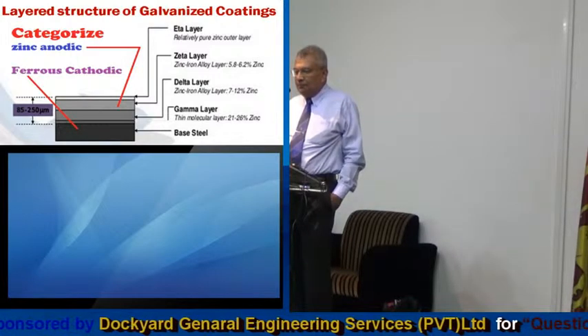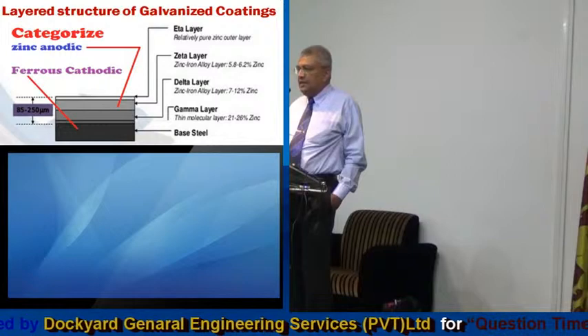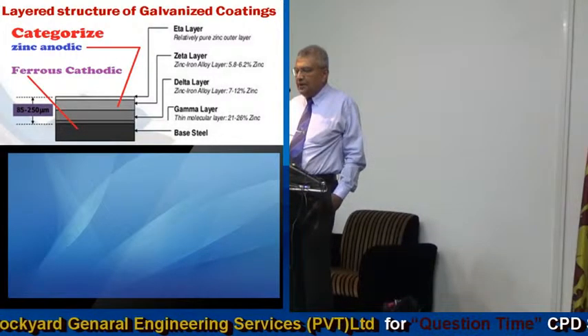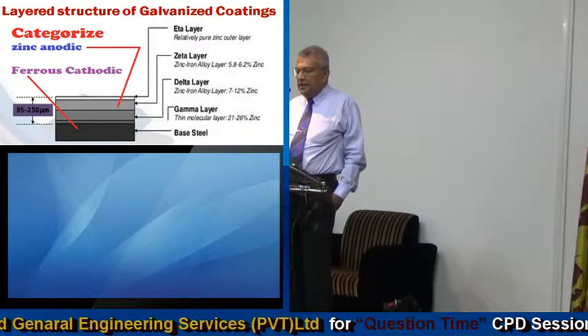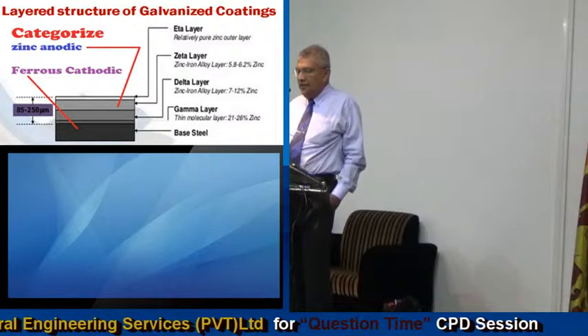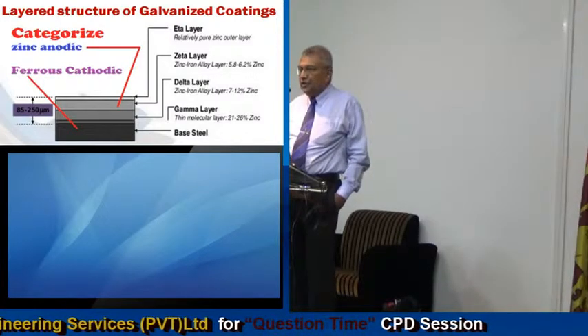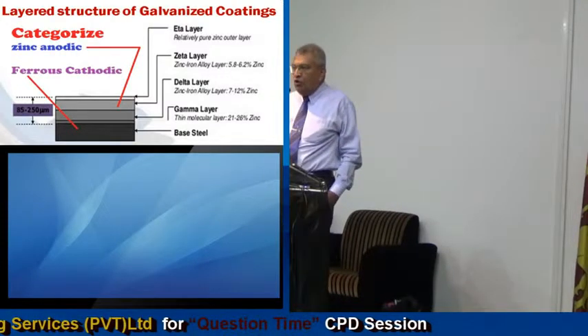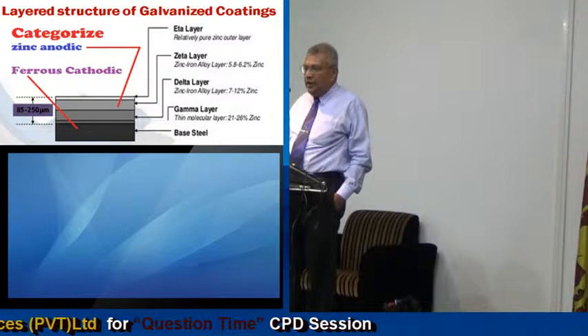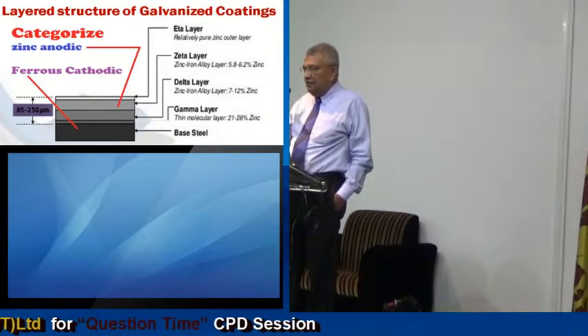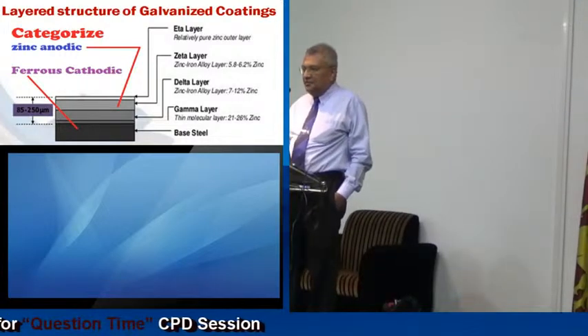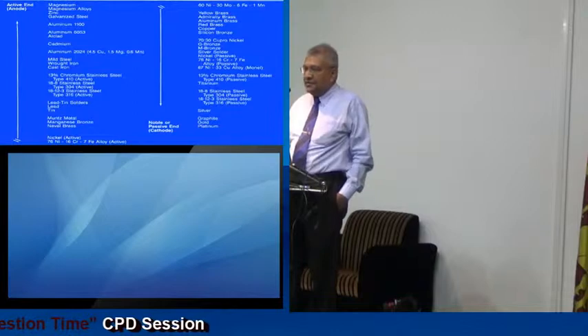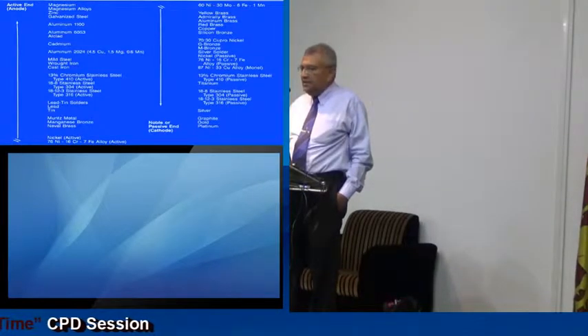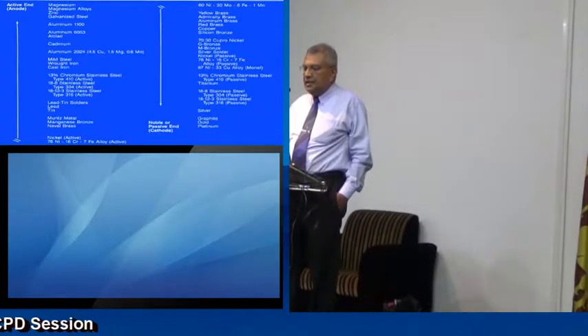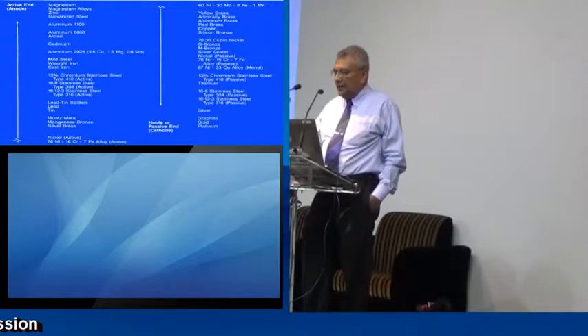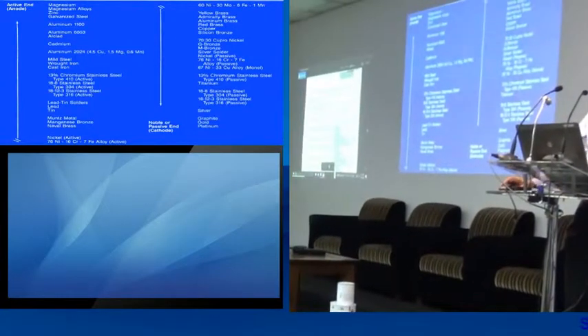We will show you why you have to paint it. This is a cross section of the galvanizing. As you see, the base steel, then the gamma layer, then the delta layer, zeta layer, and the eta layer, which is 100% zinc. Now that is the DFT, 85 microns or 250, whatever thickness you build. Now we know the ferrous is always cathodic and the zinc is always anodic. So we have a combined couple put together, because the anode always sacrifices in front of the cathode. So this is the sacrificial action here. The anode is zinc, and the steel is the cathode, and you find the steel is protected from corrosion.